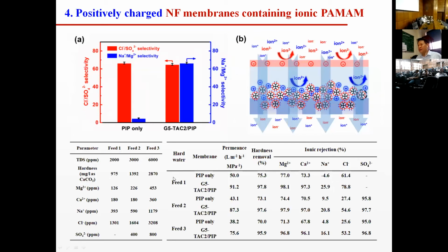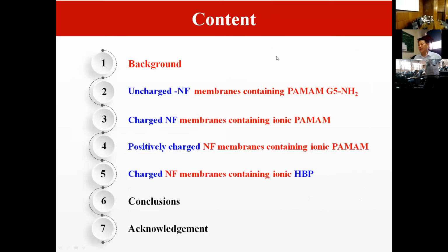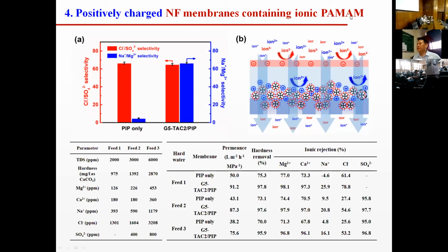And okay, this is the effect of the membrane used for separation of mixed inorganic salts. In previous reports, many researchers just used a single salt solution to investigate the salt separation property. But in our work, we use mixed salts, and we found this membrane also behaved with very high separation property for very different anionic states. So from the results above, we can find that PAMAM should be a very good candidate to prepare nanofiltration membranes with higher flux and higher selectivity.